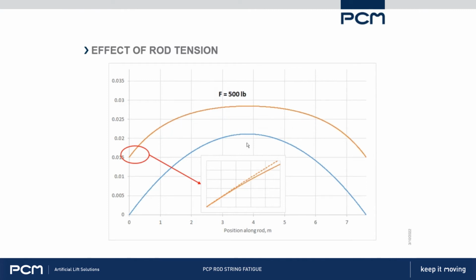Our y-axis, this tubing is offset by a little bit more than 2 centimeters, less than an inch. So over 25 feet, the tubing is offset by less than an inch. That's a 5-degree dogleg. It's actually quite a small curvature when you look at it.